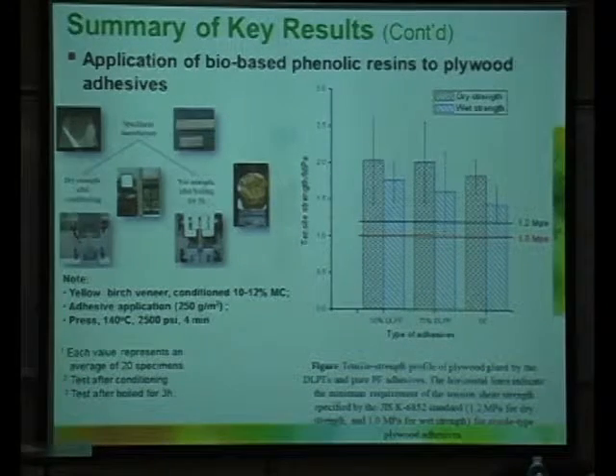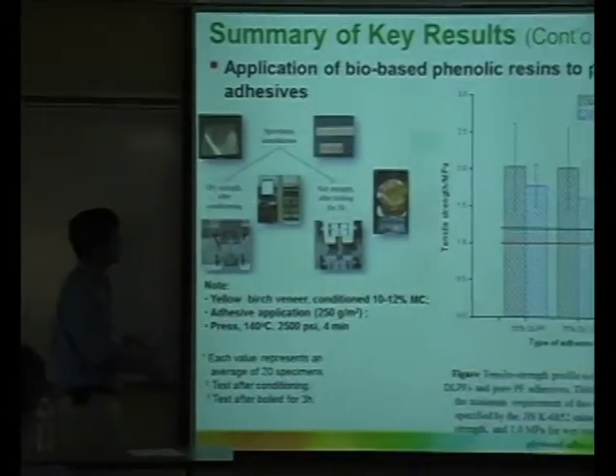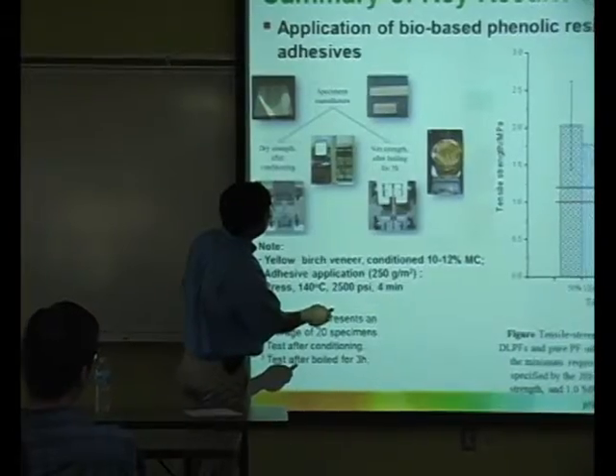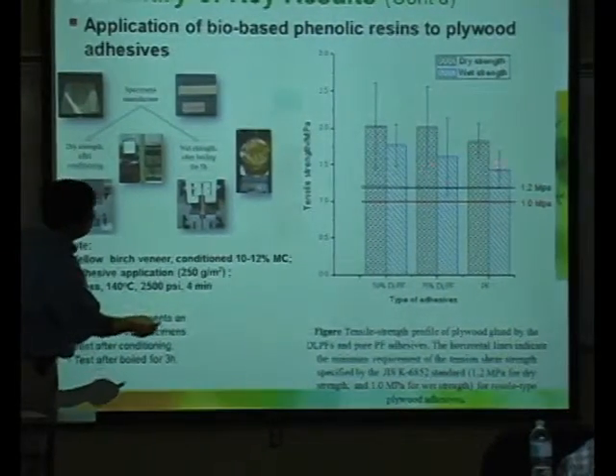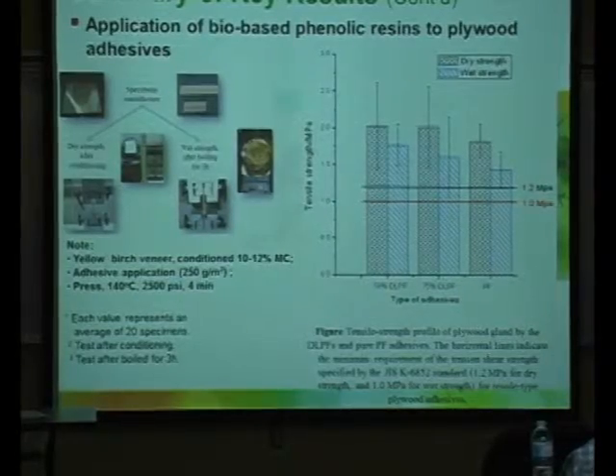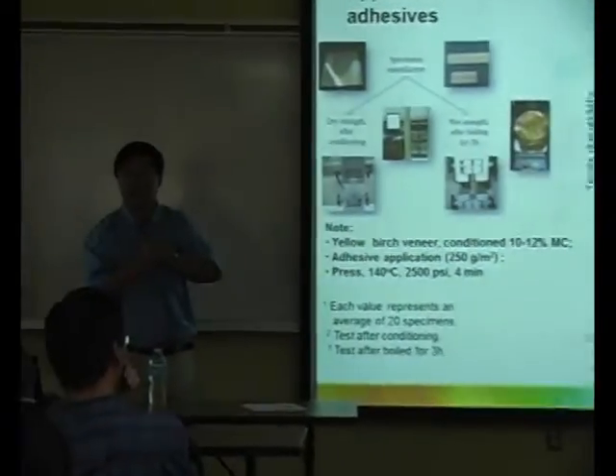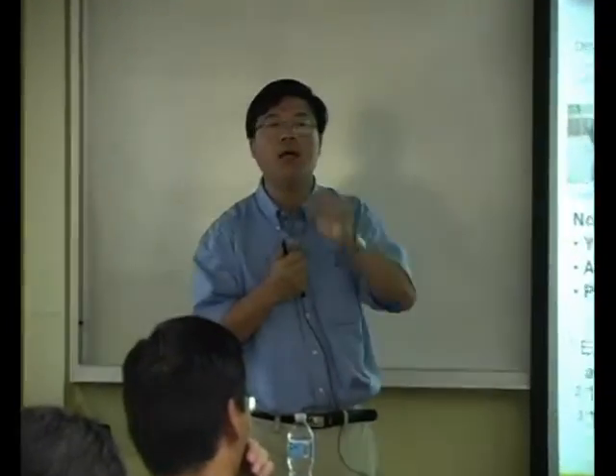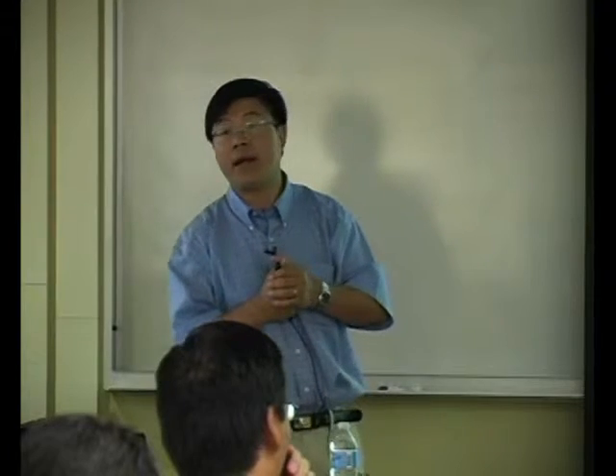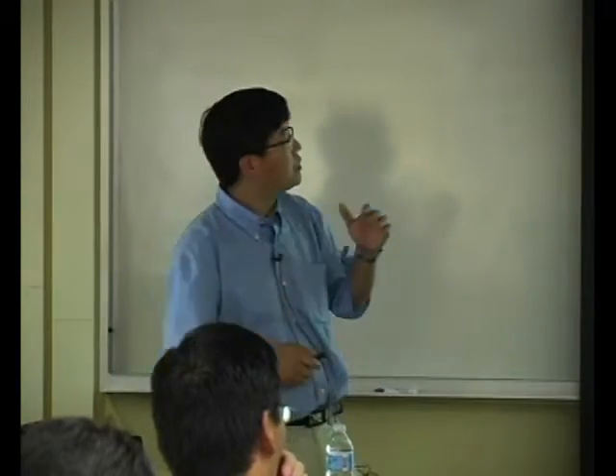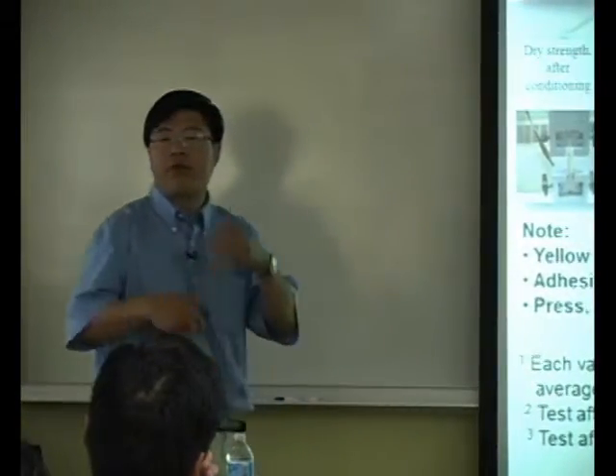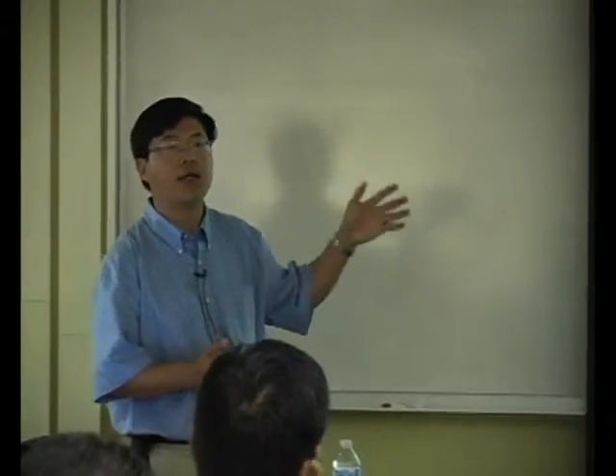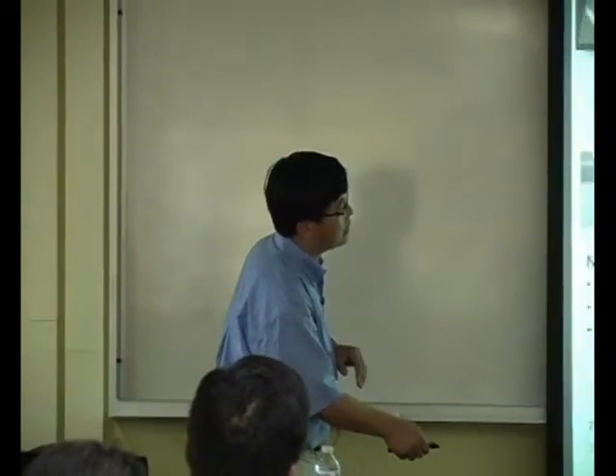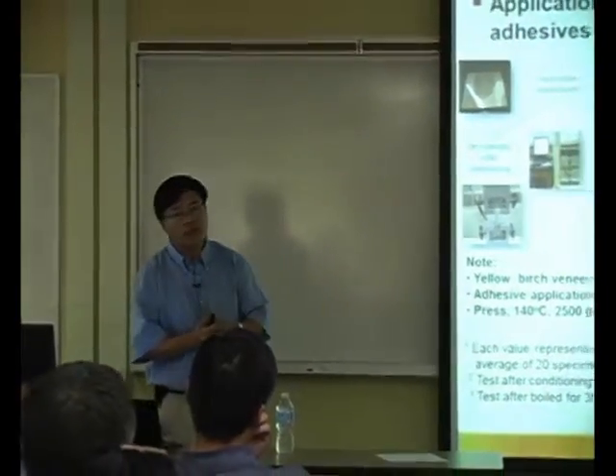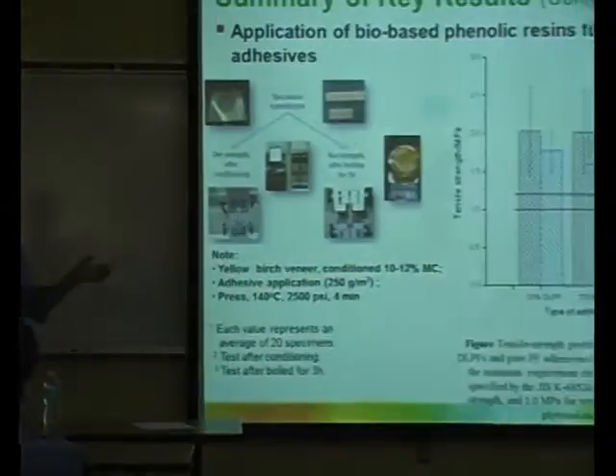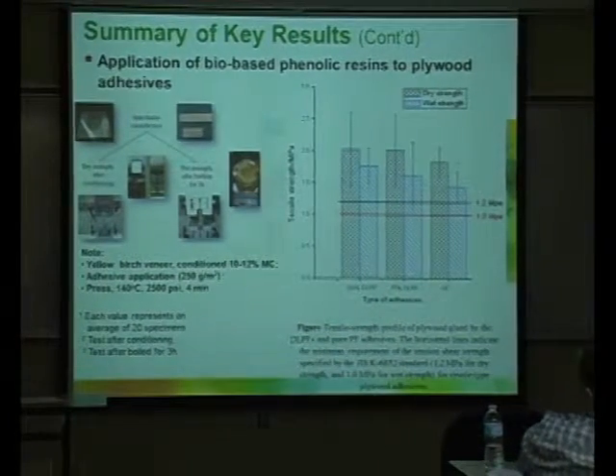So in terms of green feedstock, 75% of the components are green-based. So the dry strength and the wet strength, both of them are actually better than the control, which means that the natural-based adhesive has strong bonding, even stronger than the petroleum-based resin and adhesive. The industry is really interested in this result, and some of the commercialization is down the road. We even test 100% DLPF. The bond strength is still not bad. So for the resin, we can get rid of petroleum totally.